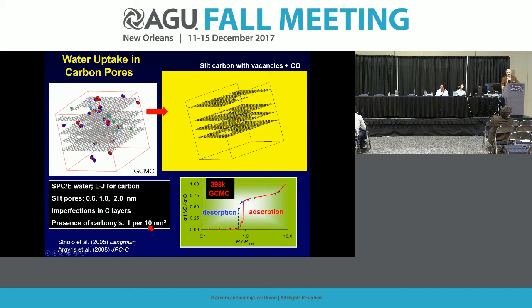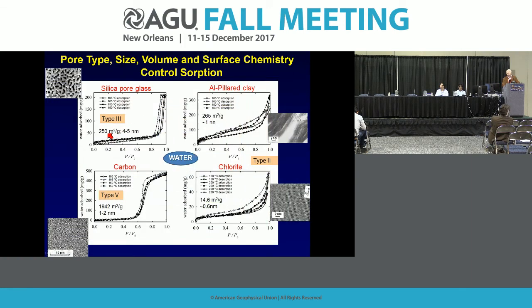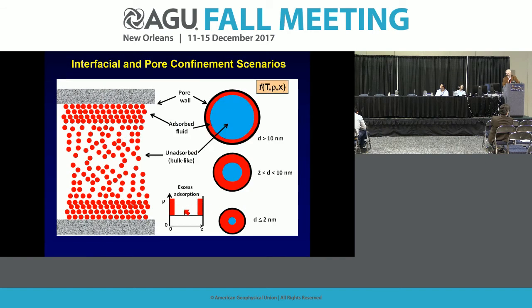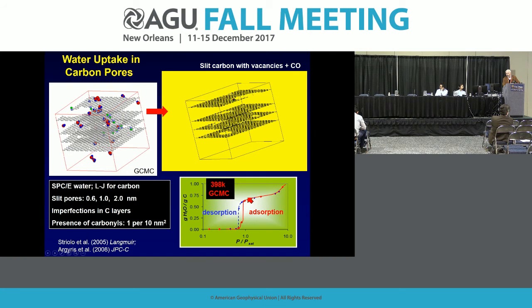Case in point, we'll take a look at the carbon case. If you go back one, you'll see this shape right here. We have very little coverage and then a capillary condensation. You'll see in this one here, this is the simulation that we ended up getting. We did a very straightforward grand canonical Monte Carlo simulation of water in these different kinds of carbons. We decorated them with carbonyls and some defects to give them a more realistic, natural look. We used a certain water model, and they had different thicknesses of the different pore sizes. Anyway, what we're going to see in the video is how this fills and how it desorbs during the process of filling at 100 degrees centigrade.